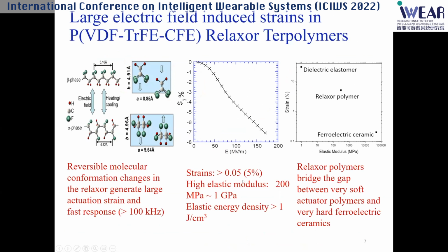This is also different from many polymer-based materials, for example the dielectric elastomer, whose modulus is only 1 megapascal. This material has a relatively high elastic modulus, between 200 megapascal to 1 gigapascal. So it bridges very nicely between the hard PZT ferroelectric ceramics and a very soft dielectric device.